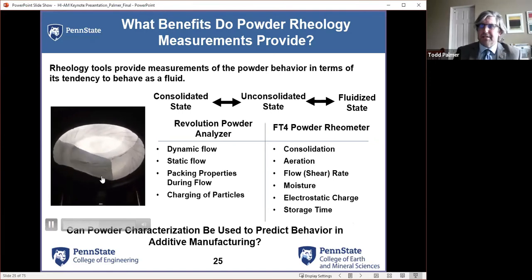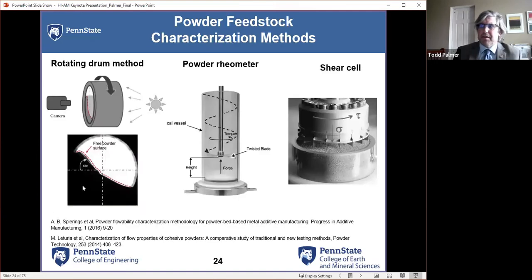And so what you're doing is you see how the powder is acting like a liquid. It climbs up the side and then it collapses down. That gives you an idea of what we consider the avalanche angle or the avalanche energy. And so by measuring that angle, it gives us an idea of the flowability. Another way is to take a blade and run it through a column filled with the powder.